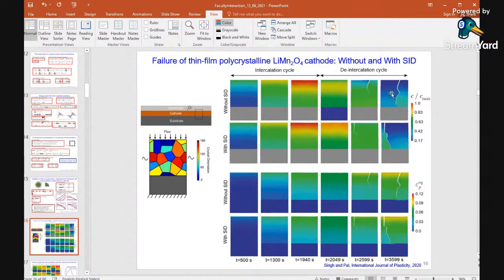Okay, and you see that the concentration gradient is not uniform during the de-intercalation. We have two different types of crack developed in this case, and we also see how the plastic deformation is generated within the structure. This fracture occurs due to the plastic deformation, because during intercalation the plastic strain is developed, which is compressive, and then when you de-intercalate, due to the plastic deformation a tensile stress field is generated, and that's the way it develops the crack.